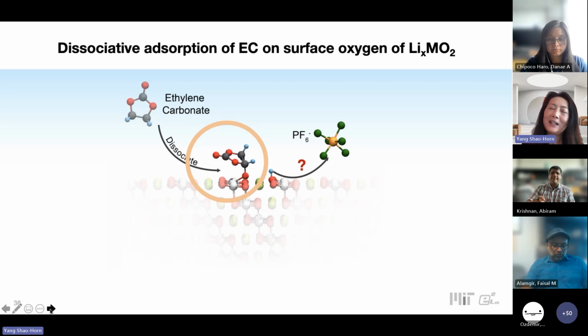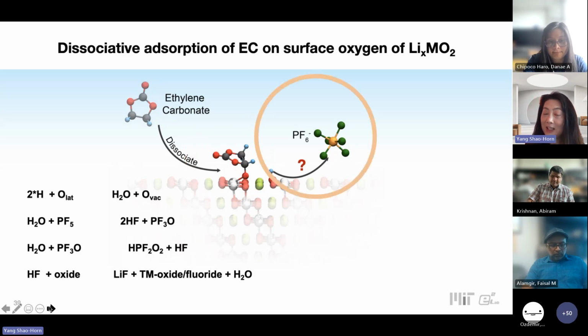Right. So essentially, we have carbonate electrolytes or carbonate solvents. They can be activated. We have CH bond activation on the surface oxygen site of nickel-rich oxide. Upon adsorption, it would dissociate another hydrogen on a nearby oxygen site. And this hydrogen becomes a proton and simultaneously reduces the nickel or the transition metal on the surface. And having a protic species, essentially we can have a generation of HF with anions, and then this would lead to a dissolution of the transition metal and generation of passivating organic films that build impedance.